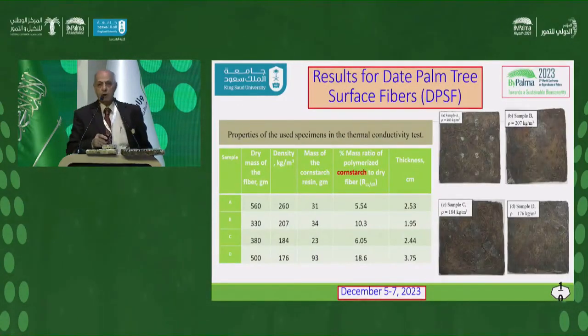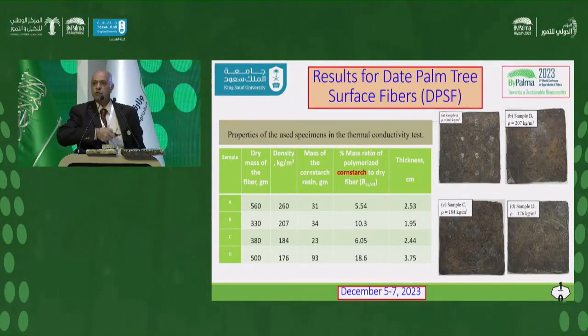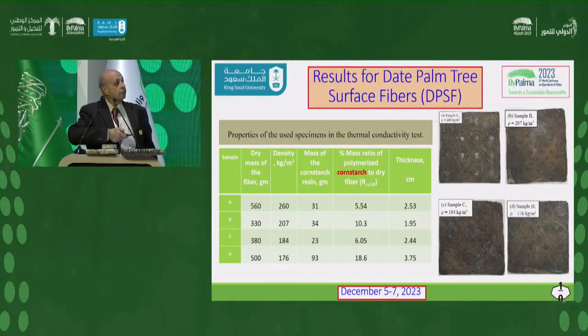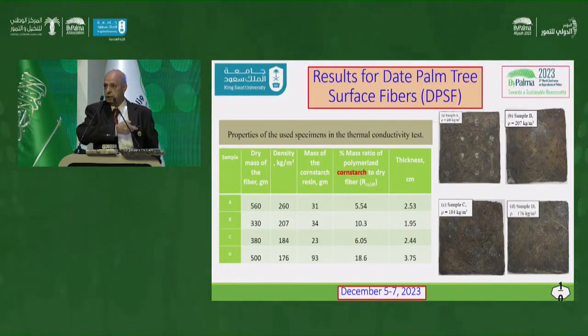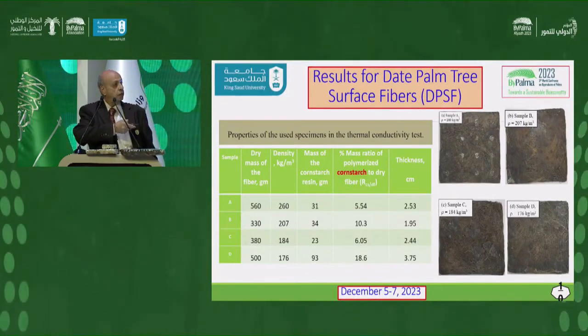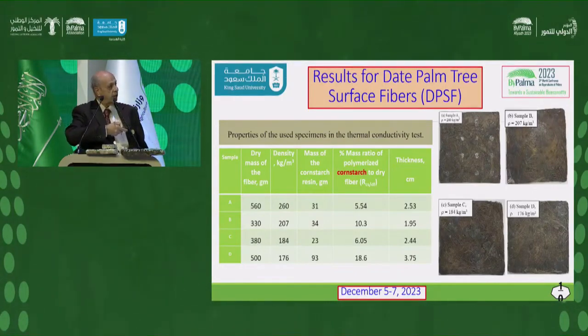Now we start our major talk, which is the palm tree surface fiber. We have done 4 samples, and we used cornstarch as a binder. So everything is natural. We are not using any chemical treatment at all. We just use cornstarch solution with different concentrations, and we have done 4 samples with different densities. Okay, A, B, C, and D.